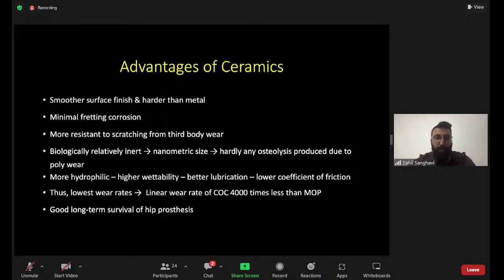So what are the advantages of ceramics? It has a smoother surface finish and it is harder than metal. There is minimal fretting corrosion and it is more resistant to third body wear. It's biologically inert. So what do I mean by biologically inert? Is that there is hardly any osteolysis produced due to the wear. It's more hydrophilic, it has higher wettability and better lubrication with a lower coefficient of friction. So all these factors give ceramics the lowest wear rate, and it has a linear wear rate which is 4,000 times less than metal on polyethylene, and that is what ensures good long-term survival of this bearing surface.